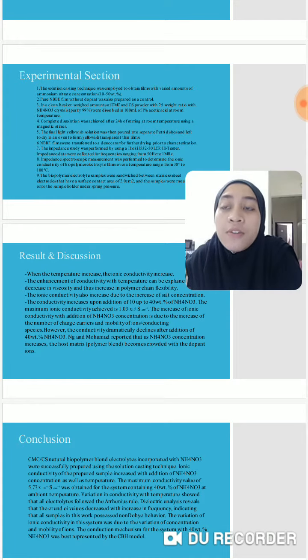Basically, from the result of this experiment, when the temperature increases, the ionic conductivity increases, because the enhancement of the conductivity with temperature can be explained by the decrease in viscosity and thus increase in polymer chain flexibility. The ionic conductivity also increased due to the increase of the salt concentration. So the conductivity increases upon addition of 10 up to 40 weight percent of ammonium nitrate. The maximum ionic conductivity achieved is 1.03 × 10^-5 Siemens per centimeter.